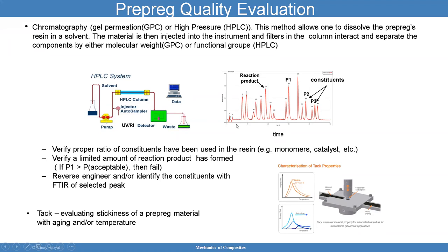here you have the information that will give you the constituents that you have in this material. It can verify proper ratio of constituents, which constituents make up that resin, the catalyst, the monomers. It verifies the amount of reaction product formed, whether it's acceptable or not. You can also reverse engineer and identify the constituents with an FTIR to make sure that you actually do have the right materials as it was told.